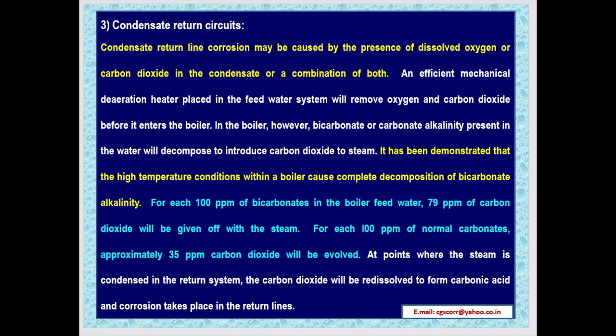The third main factor is condensate return circuits. Condensate return line corrosion may be caused by the presence of dissolved oxygen or carbon dioxide in the condensate or a combination of both. An efficient mechanical deaerating heater placed in the feed water system will remove oxygen and carbon dioxide before it enters the boiler.